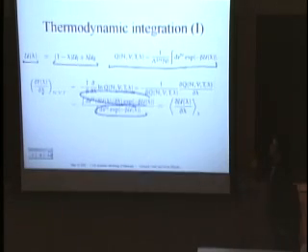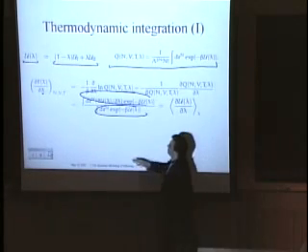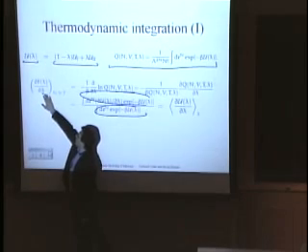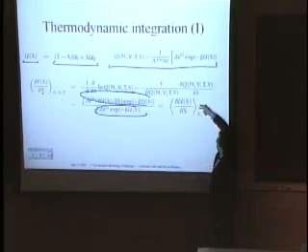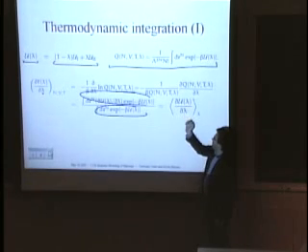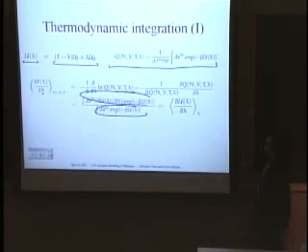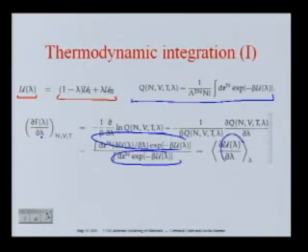So in order to calculate the derivative of the free energy with respect to lambda, you need to calculate the thermodynamical average in your ensemble of the derivative of the energy with respect to lambda. This is a quantity that you can always calculate, and it is just an average over your ensemble. So let's look at how this is done in a specific case.